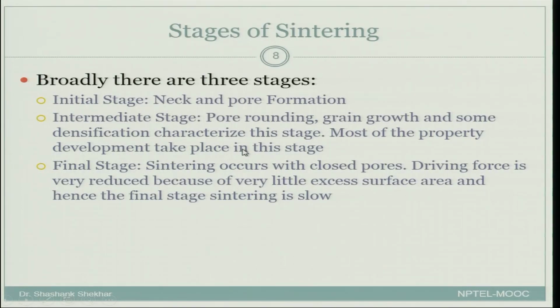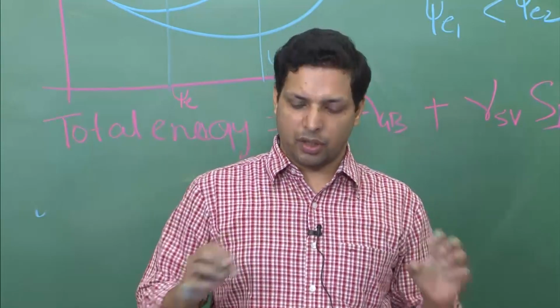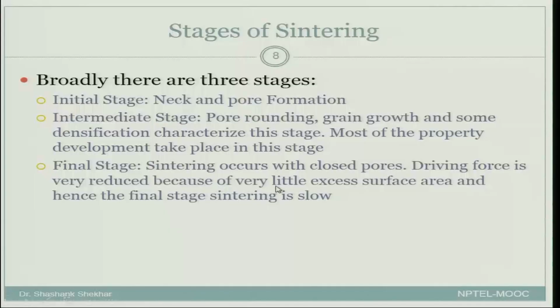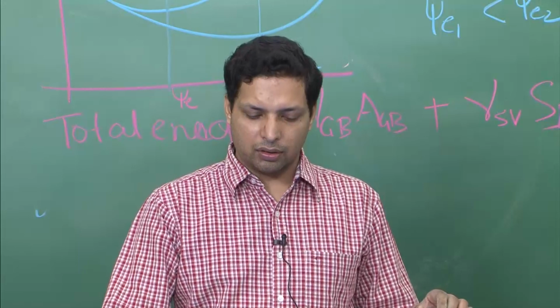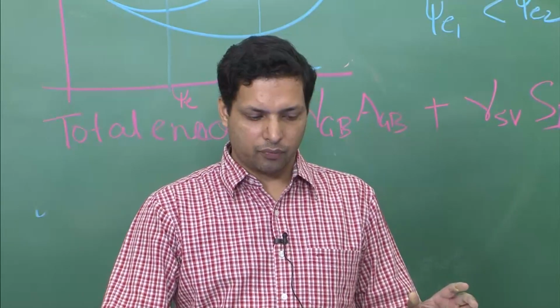Most of the property development of the material takes place during this stage, and in the final stage, where initially now in the end of second stage you had network of pores, cylindrical pores joining from here to there. In the final stage, sintering occurs with closed pores. So, now the cylindrical regions get closed, and only at the nodes you will have spherical pores remaining. Driving force is very reduced because of very little excess surface area, and hence the final stage sintering is slow. So, here the sintering becomes even slower because the overall driving force has reduced, surface area has reduced.